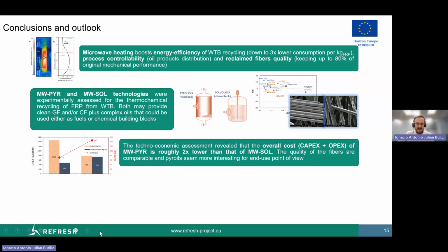And the techno-economic assessment reveals that the overall cost of pyrolysis is roughly 2 times lower than that of solvolysis. The quality of fibers is comparable between them, especially if we apply the post-combustion treatment to the fibers from pyrolysis, while the oils from pyrolysis are more interesting from the end use point of view.